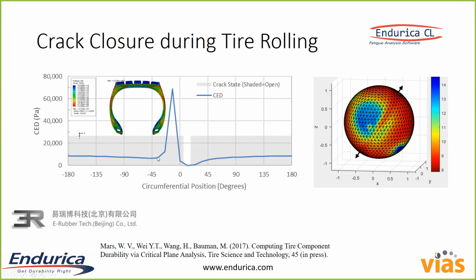As we approach the footprint of the tire, there's some bending, right? You're taking a round structure and you're applying some bending to flatten the structure out through the footprint. That causes the loads at the belt ending to experience a spike as it enters the footprint and goes through the footprint. On the other side of the footprint, as that bending is reversed, that crack that opens on one side of the footprint actually becomes completely closed. And you can see that by looking at the crack state output from Endurica, which I've plotted as this gray bar. So you can see most of the time this crack is open, but there's an instant on the exit of the footprint where that crack closes. And of course, a closed crack doesn't grow unless you're shearing it, and so we account for that crack closure effect.